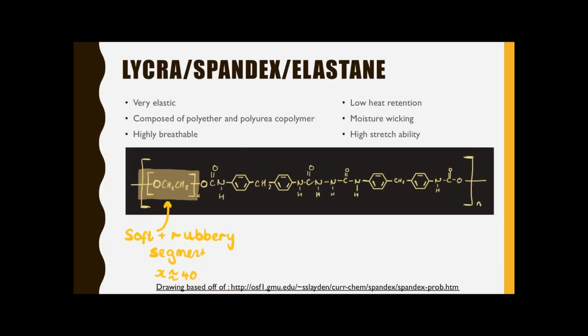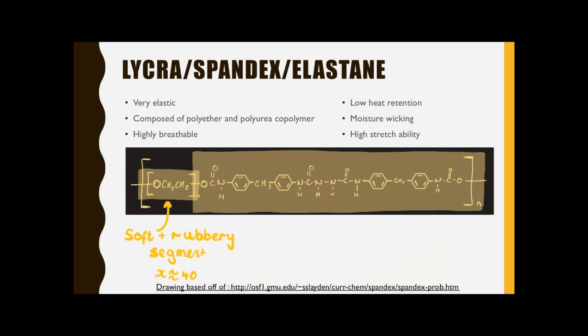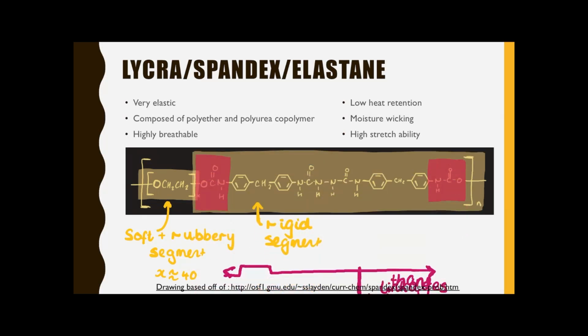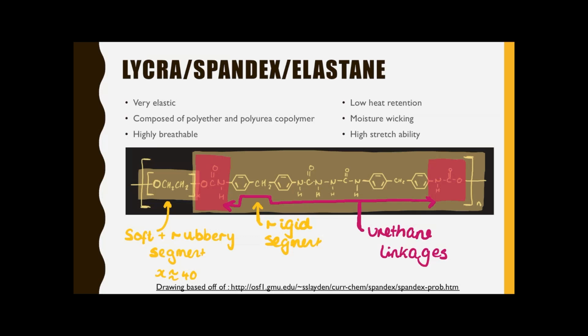It's composed of a soft rubbery segment and a rigid segment. There are urethane linkages which actually link these two together. These urethane linkages will actually form hydrogen bonds with other chains and therefore cause the rigid segments to align. This allows the soft rubbery segments to stretch up to 600% more than its original shape. This is why lycra is super stretchy.